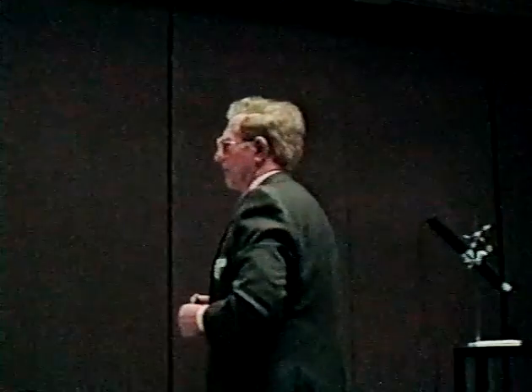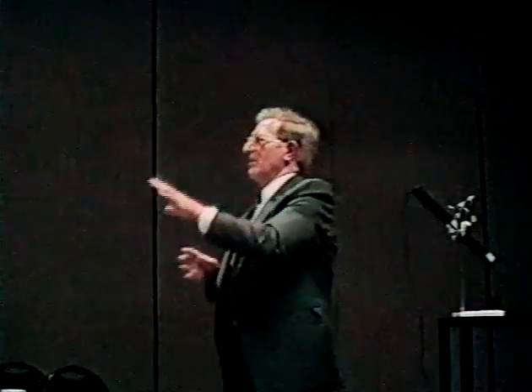And then the other side is a close packed of oxygen. Cations could sit there, I guess, but why would they want to sit together in such a concerted way? Zinc oxide is a hexagonal structure. It's basically a hexagonal diamond. And you can indeed terminate the hexagonal diamond on the basal plane by zincs only here and oxygens only here. But what I have shown on my slide were the side surfaces, which have alternating zinc and oxygen.